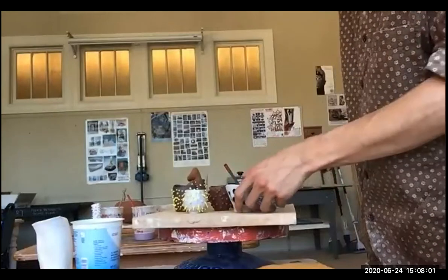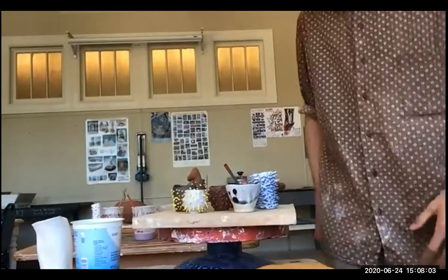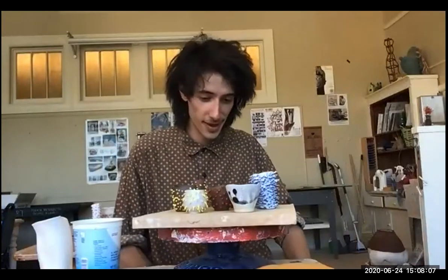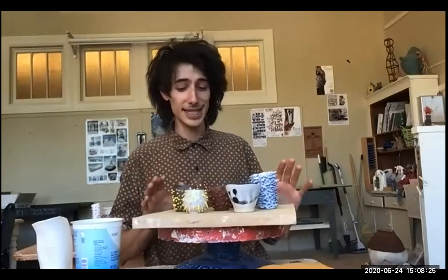So I use glazes with silicon carbide, but in that example that you showed, did you say that you added the silicon carbide to the slip? More or less, although again, it's not really slip because there's only 5% clay. It's mostly glass formers. It's more or less an under-fired glaze that I can build with. And unfortunately, I'm not really going to give you guys the recipe.